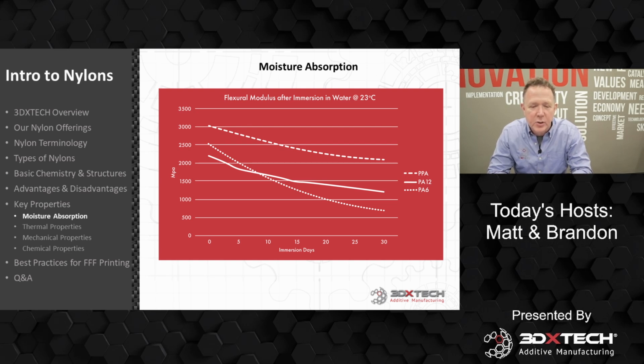And again, with the PA12, it starts off a little bit lower than PA6, but actually ends up with a little bit better properties than PA6 does after full immersion for 30 days.